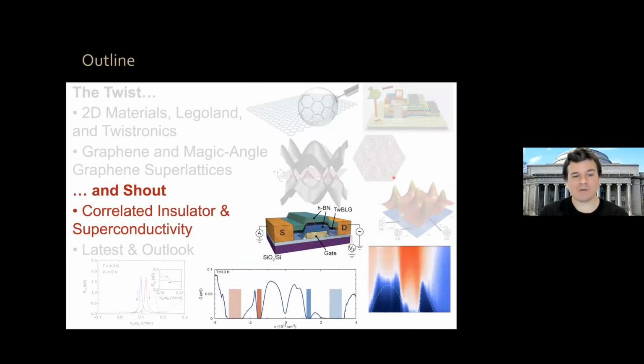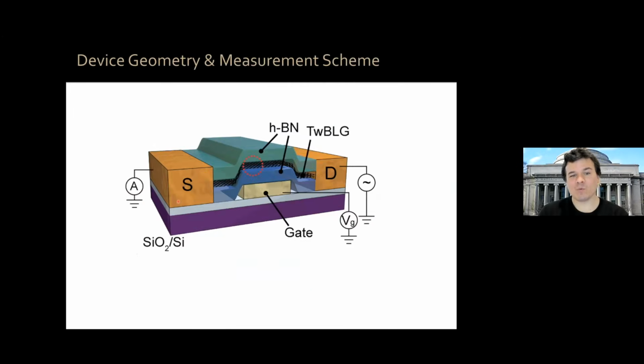So now, okay, and here comes the shout, or the beginning of the shout. We make devices, okay? And you can ask me later if you want, how do we make these devices? But let me just skip that for a moment. And we make devices where we have magic angle twisted bilayer graphene. Okay, so twisted bilayer graphene at this angle, 1.1 degrees. It's encapsulated between 2 dielectrics, 2 flakes of hexagonal boron nitride. It's a very nice dielectric for the system.